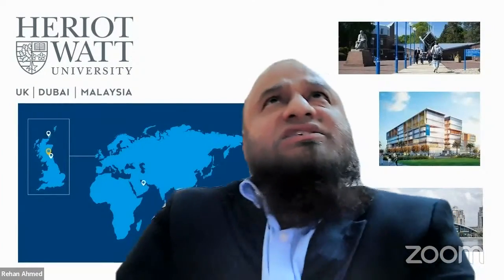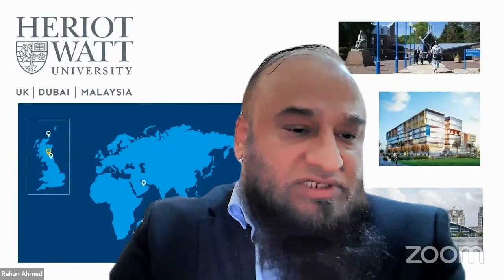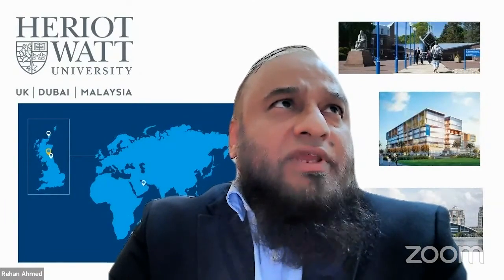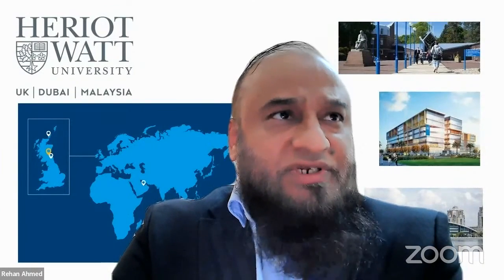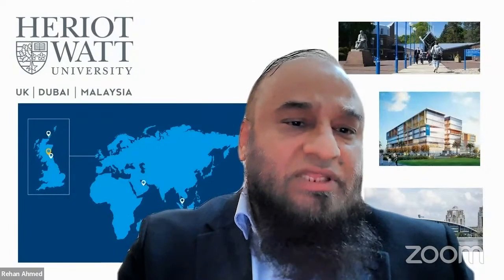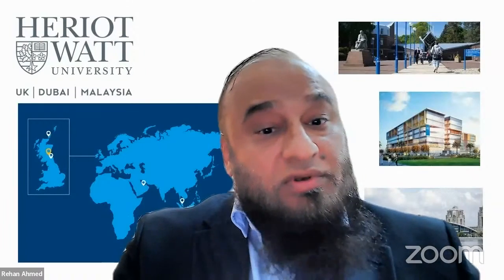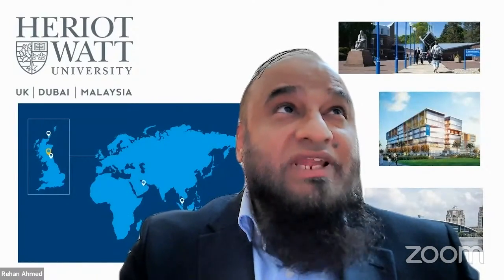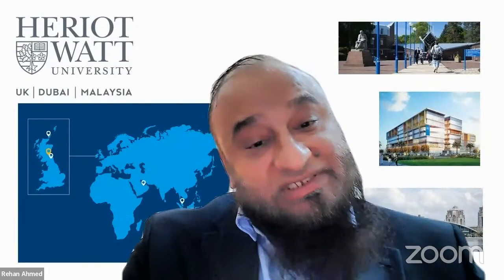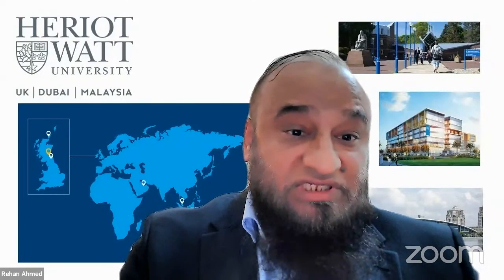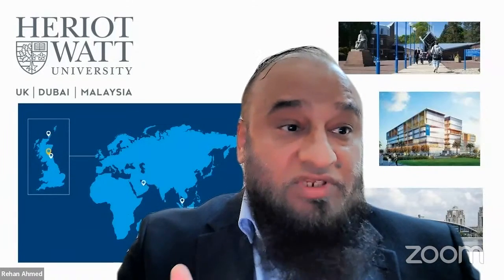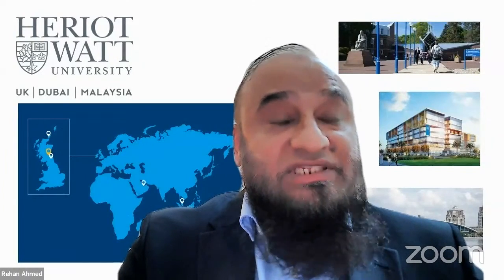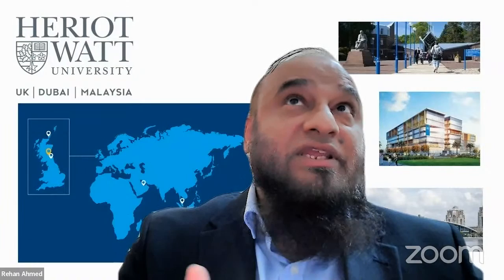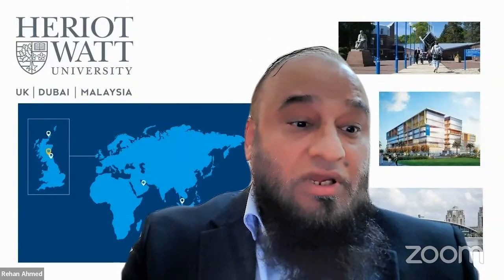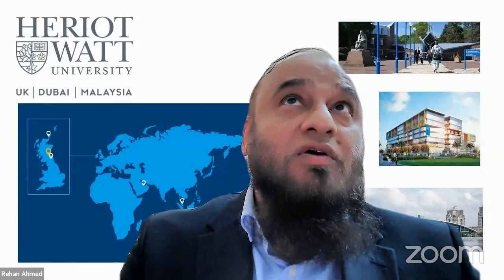Yeah, I fully understand. I think this is an area of research which is still ongoing, and it's a good question, because at the moment we are at the stage where we can couple different modeling techniques to predict residual stress, and then compare the residual stress with experimental techniques to make sure that we have some confidence in our stress evaluation. However, the question you asked is actually much bigger, because that asks about integrating this with the manufacturing process itself, which is, with the digitalization of the manufacturing process, artificial intelligence, neural networks into the coating process parameters and everything else, the future probably is where what you're suggesting, where basically you can actually use or design the coatings at the development stage to at least try and have some idea of what the stress profile will look like.